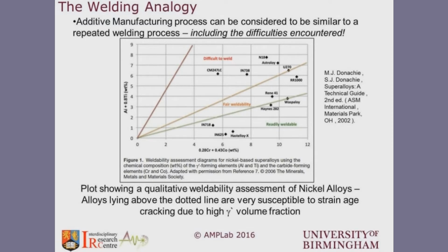What you will find is that the higher the amount of the aluminium and titanium content, we end up getting more difficulties in welding. So that qualitative classification we see on the diagram shows the typical alloys that people have used in the 40s and the 50s as alloys that are readily weldable.